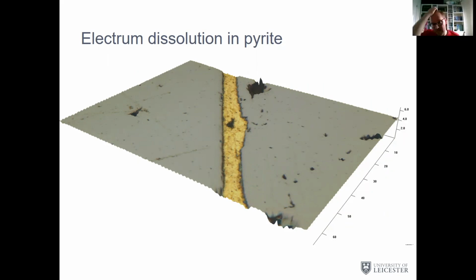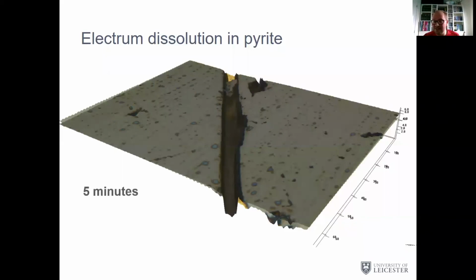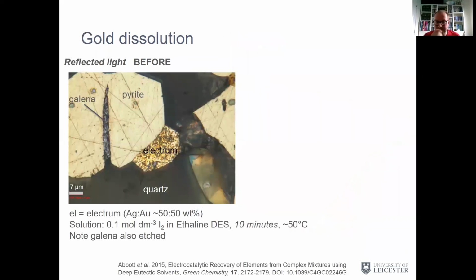So this is electrum, an electrum vein cutting through pyrite. We introduce our solvent. 5 minutes later, at room temperature, the gold is dissolved out, and then it can be precipitated by electrochemistry. We can show this for different mineral assemblages. So galena, pyrite, quartz, electrum. So this is an in situ leach, again, a polished block.